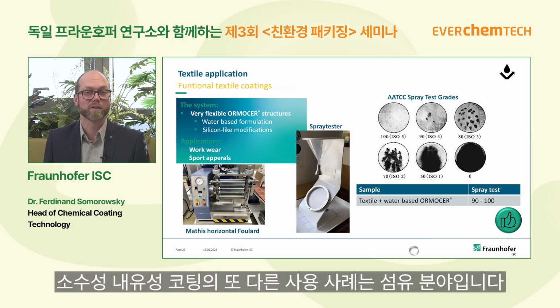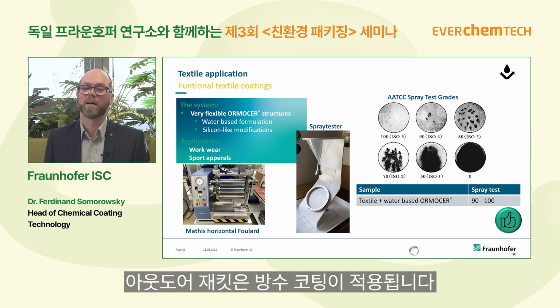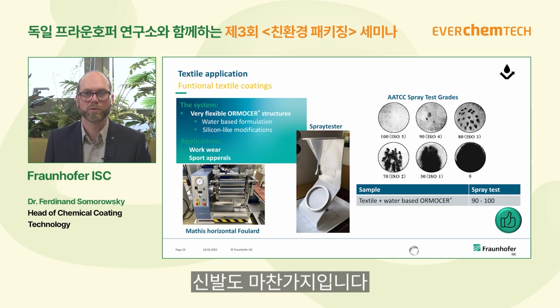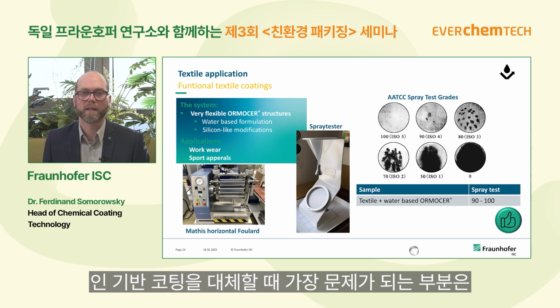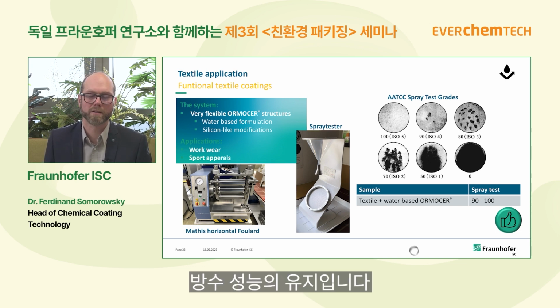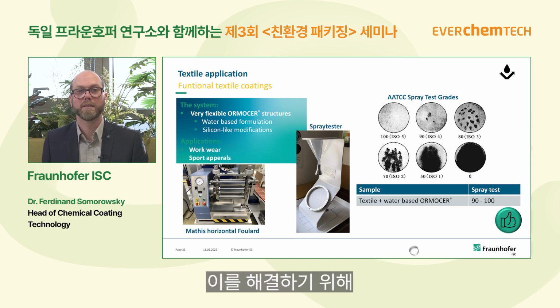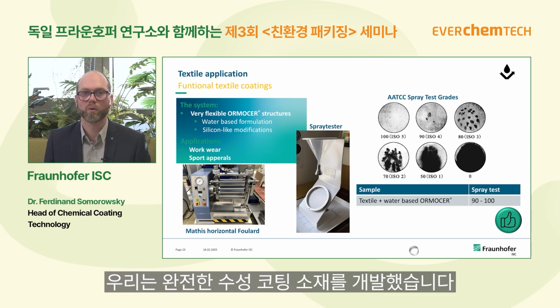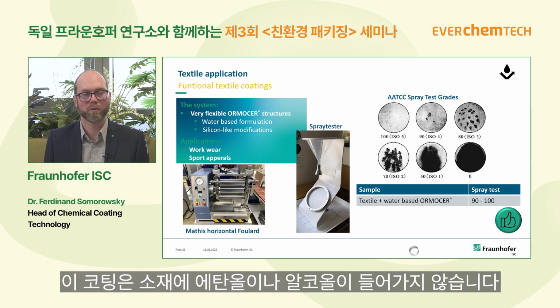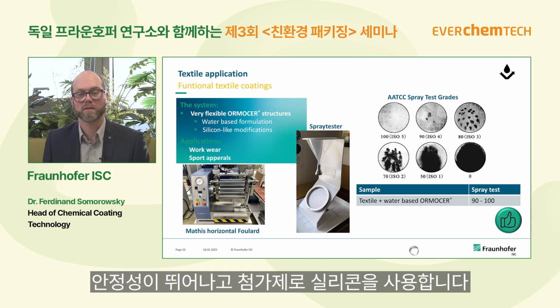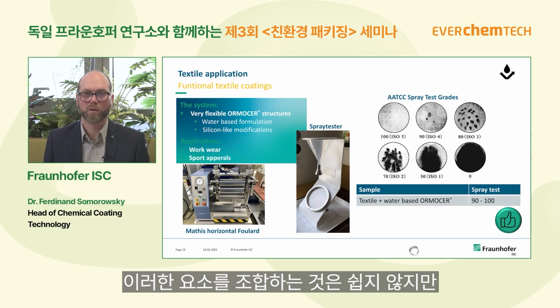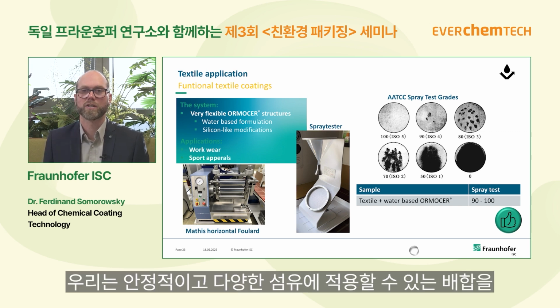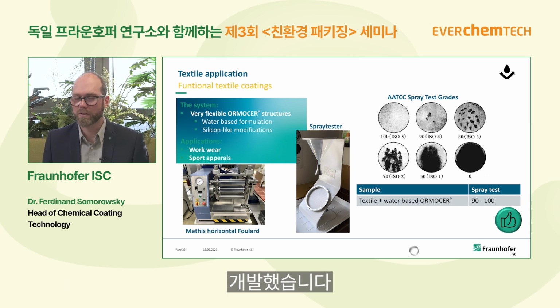Another use case for hydrophobic and also oleophobic coatings is the textile sector. We know that very well. Each outdoor jacket is coated. For example, also shoes are coated. And when we would like to replace PFAS, the main issue is the repellency towards water. Here we developed a pure water-based material. So we have no ethanol, no alcohol in the coating layer. So it's very safe, and we use silicone as an additive. It's not easy to combine this, but these formulations are stable and can be applied on different textiles.